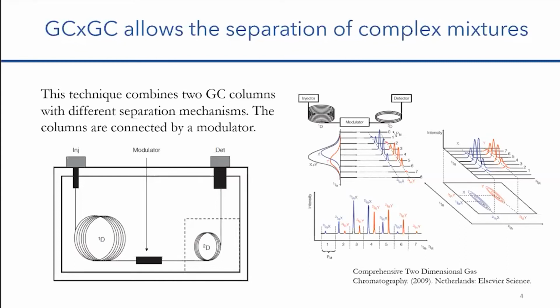a second dimension column. And the second dimension column that we are using in our lab is a column that separates by polarity. So as you can see here, this is some explanation about how GC by GC works. If we're working with just a one-dimension column, we will see this X plus Y peak. But in reality, we have two different analytes there, X and Y, and because they have similar properties, for example, similar boiling point, we are not able to separate them.